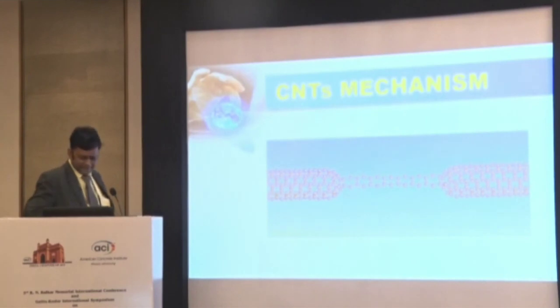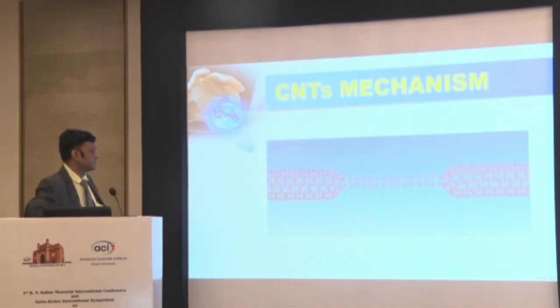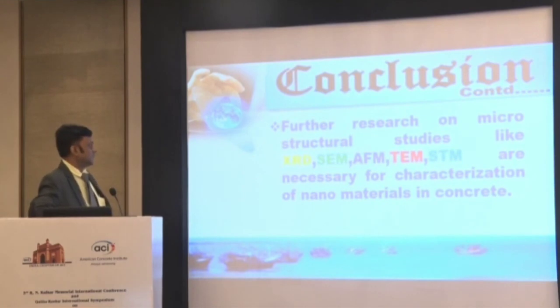Now, the CNT mechanism, why it is so: this bond is very difficult to break. That's why I am getting more strength for CNT mortar and for CNT concrete. See, much time and much energy is required to break it. Conclusion: further research on microstructural studies like XRD, SEM, TEM, STM is necessary for characterization.